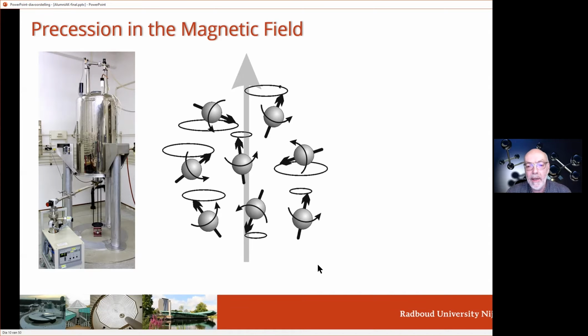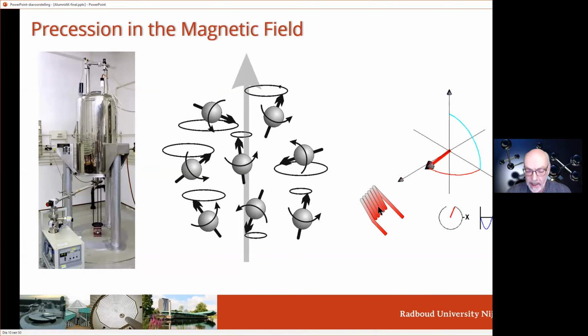And what we do in an NMR experiment, we put the sample in a coil, we put on some radio frequencies, which are resonant with the spins. That tips over this magnetization by 90 degrees. Then you just switch off your RF and you use that same tiny coil as a detector. So this precessing magnetization will actually induce a current in this coil. And essentially that is what we detect. That also precesses at frequencies in the megahertz regime. That is the basic workhorse experiment of modern day Fourier transform NMR, as it's called.